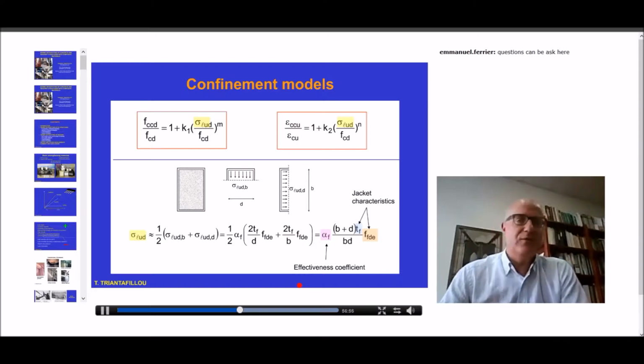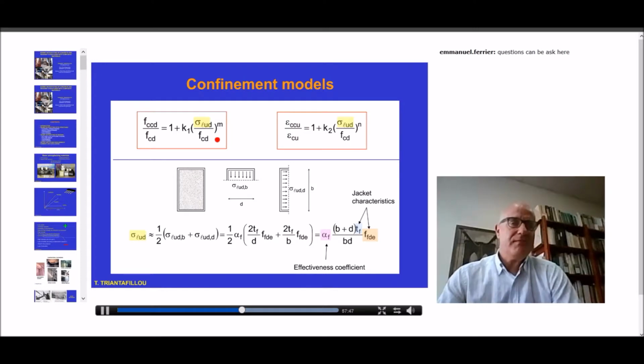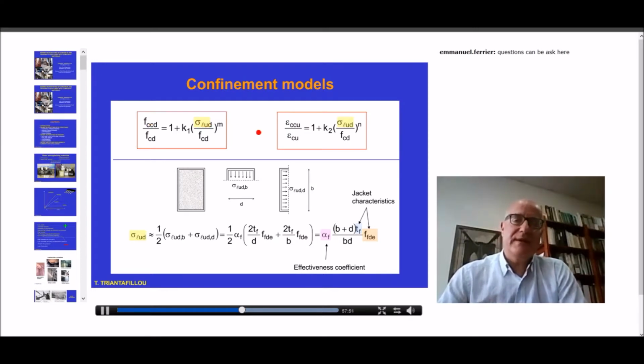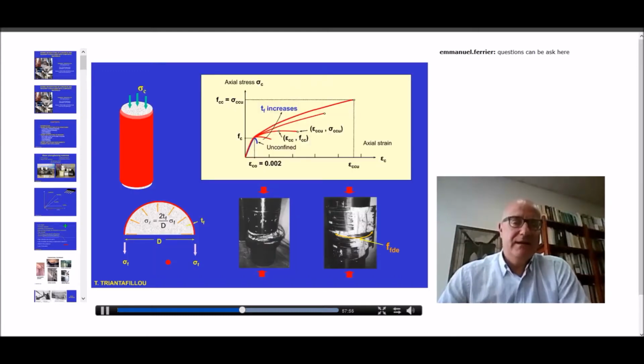To do calculations, we need to somehow quantify the response of confined concrete. That is, we need the confinement model. If you search the literature, you will find at least a couple of hundreds of those models. Nearly all of them, if not all of them, can be expressed in this way. This is a general form. For example, the equation to the left gives you the strength of confined concrete normalized with respect to that of unconfined concrete as a function of the confining stress. Here this term sigma LU, whatever design value of that, is the confining stress. And we have an identical formula for the ultimate strain of confined concrete normalized with respect to the ultimate strain of non-confined concrete. So clearly, the higher the confining stress, the higher the strength as well as the ultimate strain.